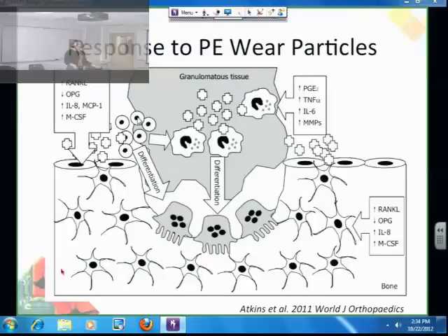They activate them to be extremely pro-inflammatory, and they make them start degrading everything in sight, because activated macrophages degrade things. They even degrade the bone, and that's why you see implant loosening after wear particles. So it's actually not failure of the material when you have osteolysis in orthopedic implants. It's actually the macrophages going haywire on your own bone and degrading it.